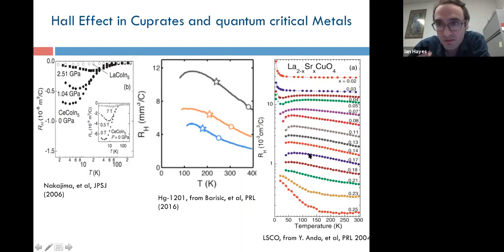And this isn't even limited to just high Tc materials. Other unconventional or quantum critical superconductors show something like this. So CeCoIn5, I have an example over here on the left, shows a strong change in RH that is strongly associated with just the critical region and highest Tc. So this does seem to be a consistent feature of the superconducting state, or I should say, superconducting materials in a broad class of compounds.